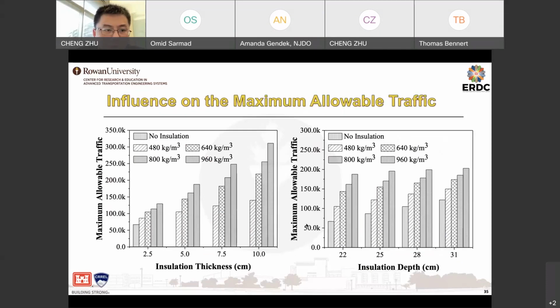And based on this cracking, we can actually calculate the maximum allowable traffic. With a higher insulation thickness, we see a significant increase of the maximum allowable traffic. And here, for the insulation depths, the effect on the maximum allowable traffic is not very obvious. This means thickness has a larger impact on improving the pavement structure's ability to resist the traffic load.